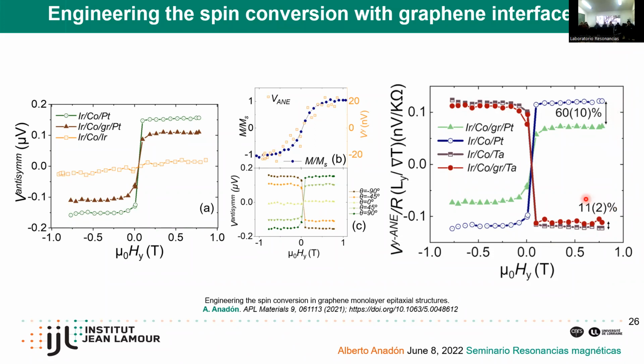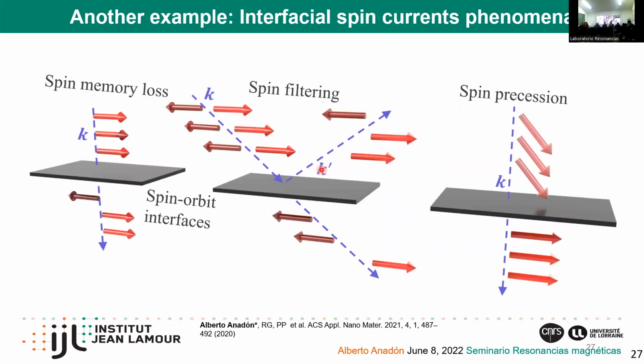But we can go further, and we can study not only what happens in 2D materials, but also in interfaces. And there are different phenomena that we can see in interfaces between different materials. So I discussed a moment ago about spin memory loss. In here, when we introduce a spin current in the system, in the interface with a spin orbit coupling, we can, for example, lose part of this spin memory, of this spin polarization, and this, as I said, is called spin memory loss. But we can also have different effects. Basically, we can have, for example, spin filtering, in which a current that can be even unpolarized in terms of spin, we can create a spin polarized current in both sides of this interface due to this Rashba interface in the system when we have an electric current in our stack.